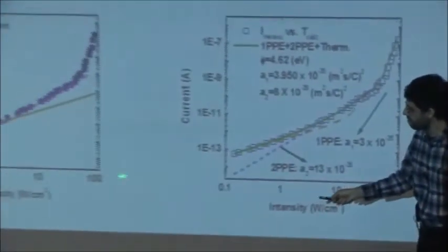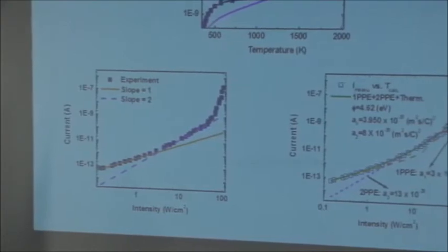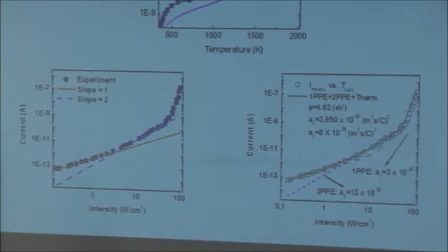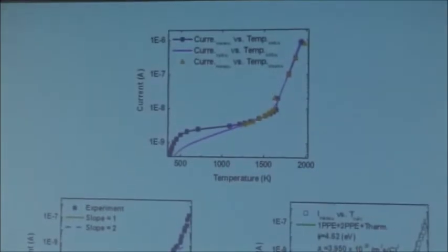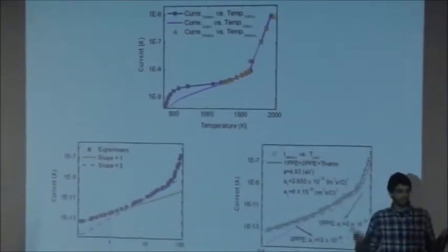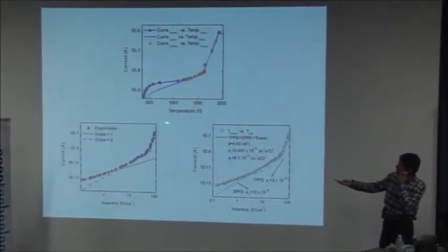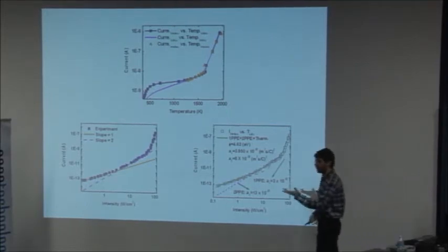So one thing that's very interesting is that now you can do an experiment where you go from a very wide range of intensity of your light and look at the current that comes out. And you realize that as soon as you go above the heat trap threshold that I mentioned, the temperature also goes up. So now you can measure the current as a function of temperature. But remember that in this case, it's not just thermionic, it's a combination of photoelectric and thermionic effects. So what you're seeing here is a sweep of emission current as a function of temperature under photoelectron emission conditions,